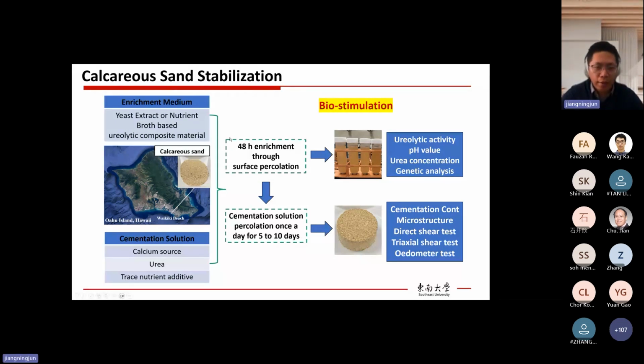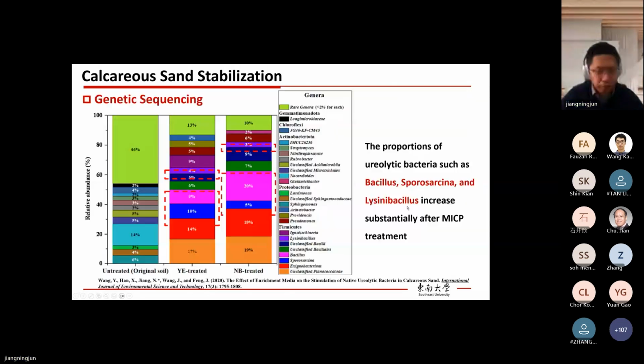For the rest of the samples, after the stimulation process, the cementation solution was applied through percolation once a day for 5 to 10 days to make the solidified soil samples. Then the soil samples were subjected to cementation content measurement, microstructure observation, direct shear test, triaxial shear test, and oedometer test to see the mechanical performance after MICP treatment.